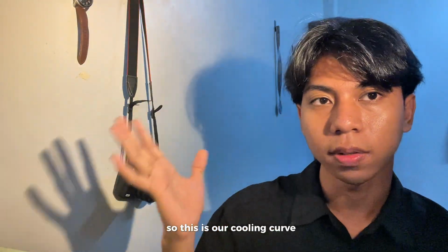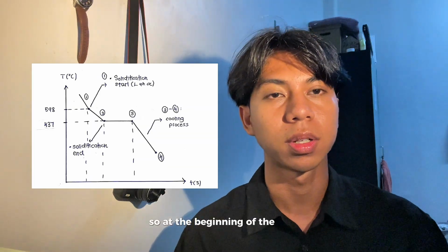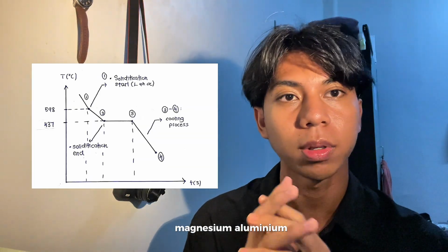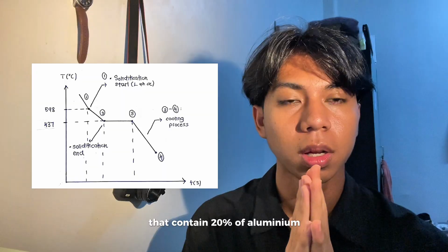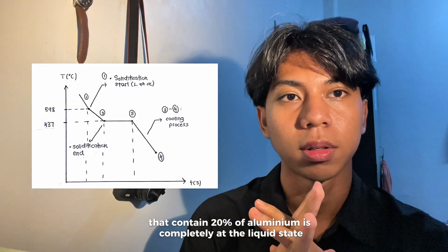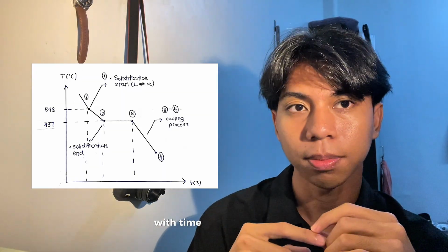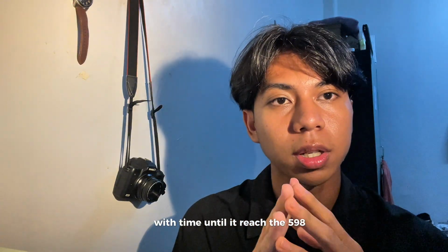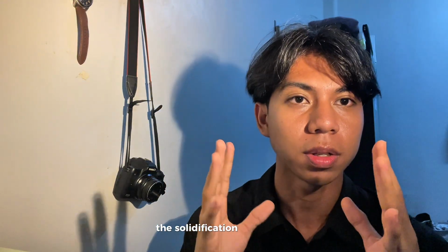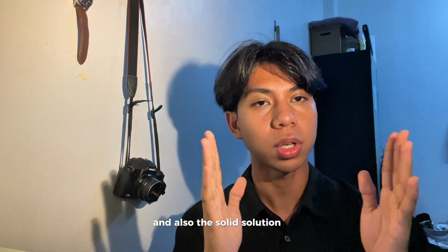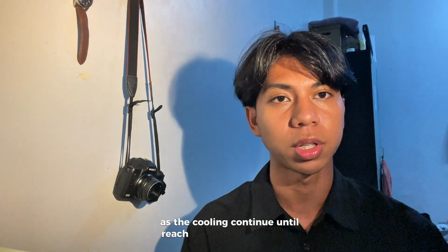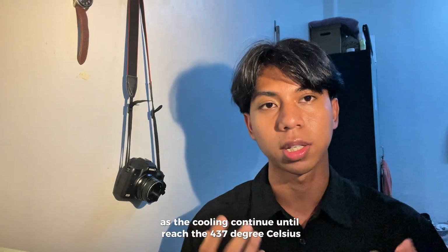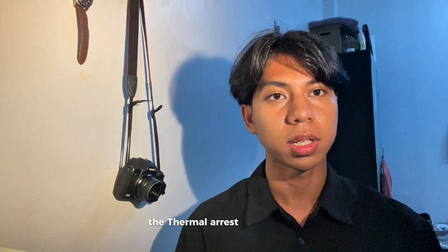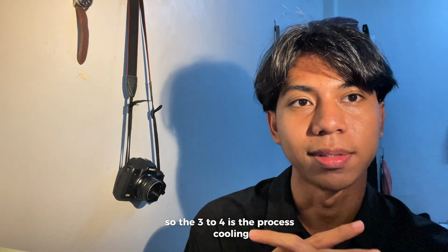So this is our cooling curve. At the beginning of the cooling curve, magnesium aluminum that contains 20% aluminium is completely in the liquid state. The temperature decreases smoothly with time until it reaches 598 degrees Celsius, where solidification begins and the solid solution starts to form from the liquid. As the cooling continues until it reaches 437 degrees Celsius, the thermal arrest appears on the cooling curve. So 3 to 4 is the cooling process.